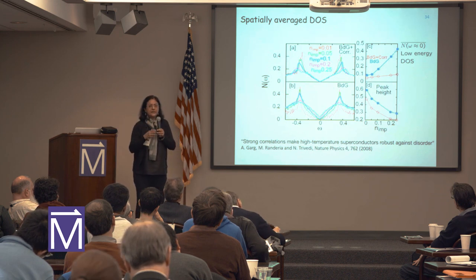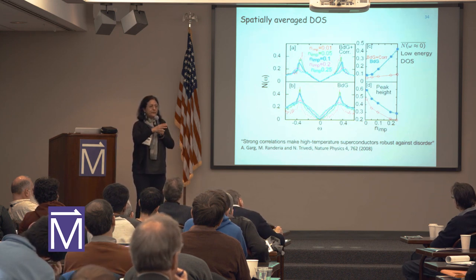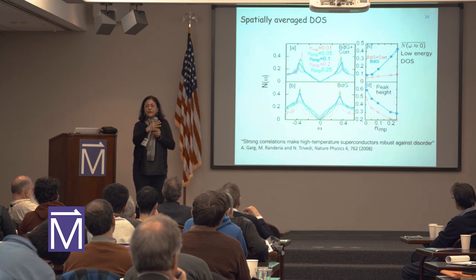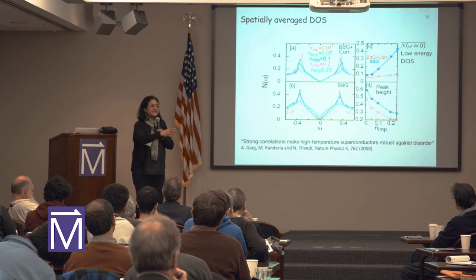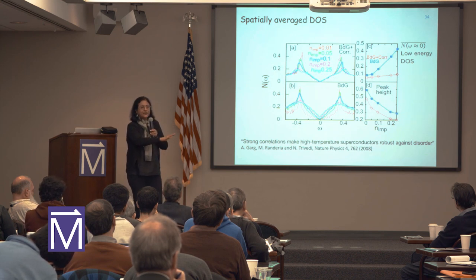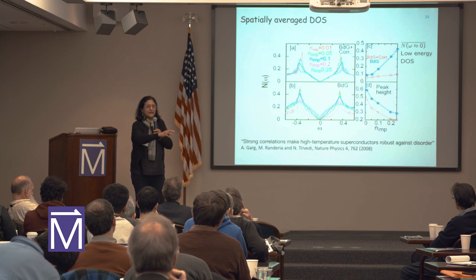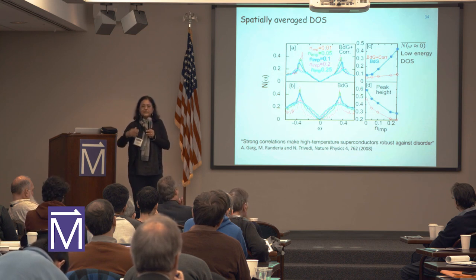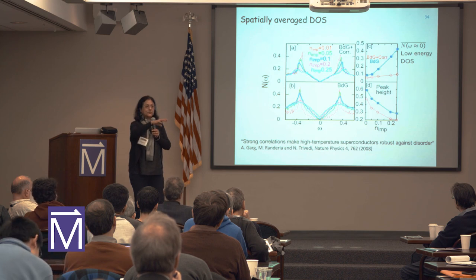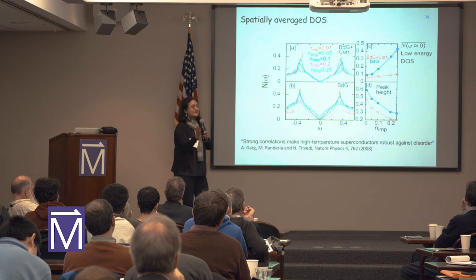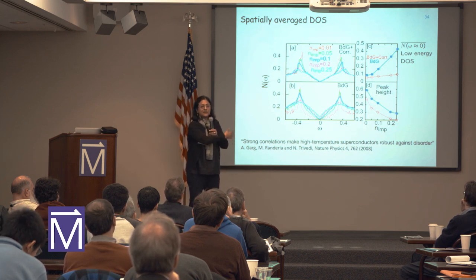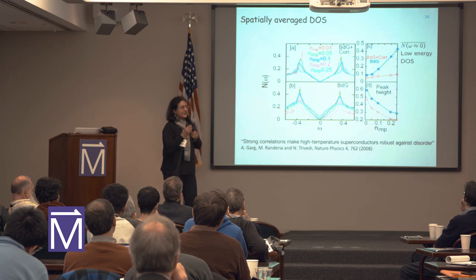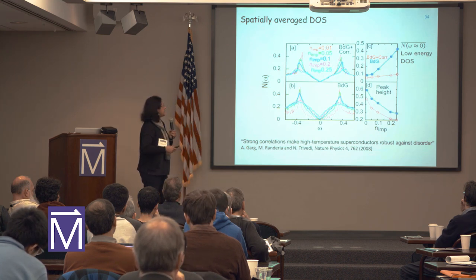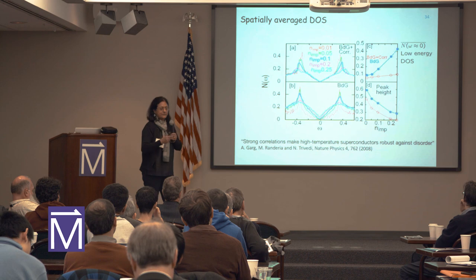But what we found remarkably was that once again, because of the inhomogeneity, superconductivity reorganizes itself. So regions that are really bad for superconductivity, that's actually insulating. And the regions where the disorder is small, that's where superconductivity tends to originate. And in those regions, indeed, you suppress internodal scattering and preserve the gap. So it's kind of this mixed K and real space picture, but it's actually very intuitive.